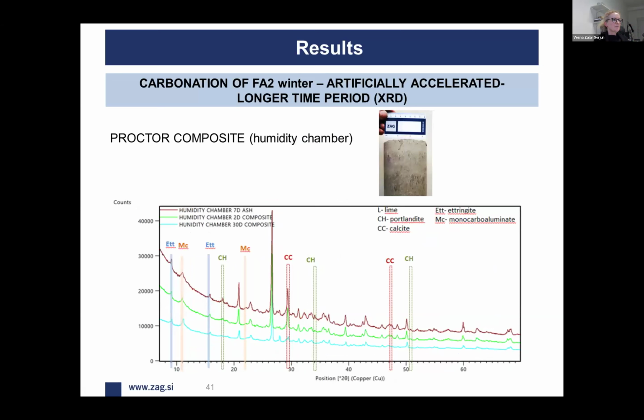Further, we made a Proctor composite from this ash, which was aged 7 days in different chambers, and then we checked the different time intervals of composites after 2 days and 30 days. In the humidity chamber, again, we can see the formation of different hydration products in the Proctor composites after 30 days. So this material is still at least in part active, but it already sequestered some CO₂, so we have two benefits.